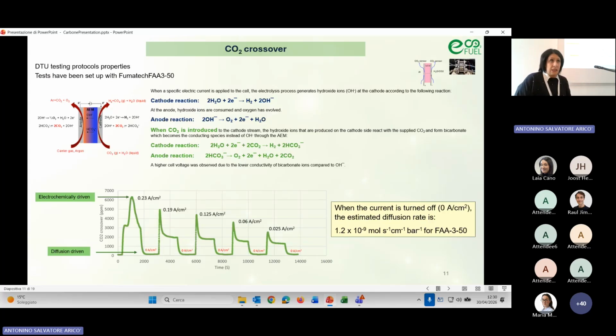This test was set up at DTU and is regarding the CO2 crossover, because, obviously, like in the previous question, crossover is very, very important. It can be detrimental for the performance. So at the DTU, they set up this method in which an MEA was created and tested in electrolysis mode. And here in blue are reported the reactions of hydrogen and oxygen evolution, but when CO2 is introduced to the cathode stream, there is the formation of bicarbonate. So the bicarbonate can migrate upon current with OH, and a mixed movement of anions can arrive to the anode side.